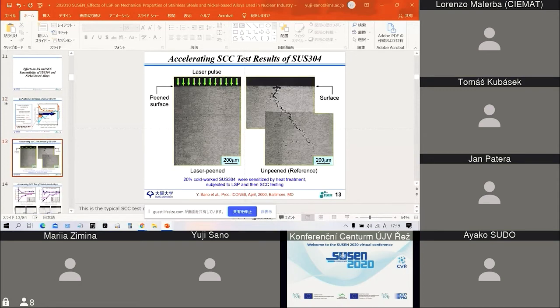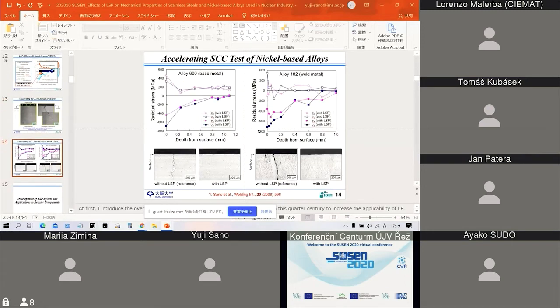This is the typical accelerated stress corrosion cracking test result of SUS304. We repeated such experiments by changing the laser irradiation condition, and we determined a certain window which can induce compressive residual stress and prevent the initiation of stress corrosion cracking. After the confirmation of the effect of LSP to prevent the initiation of SCC, this is the result on the nickel-based alloy 600 and alloy 182. Similar to SUS304, we can prevent the initiation of stress corrosion cracking by LSP.